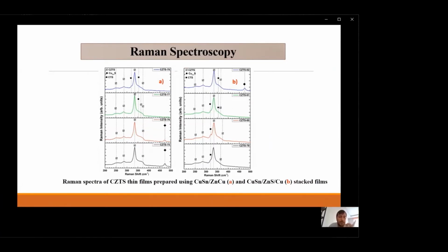As you can see, regardless of the sulfurization temperature and the stacking order, all the samples again are dominated by peaks of CZTS. As you can see, around 338, it stems from the vibration of sulfur anions in this compound. Apart from this kesterite phase, you can see at low reaction temperature some copper sulfide phase occurs, and at high reaction temperature some CTS phase occurs.